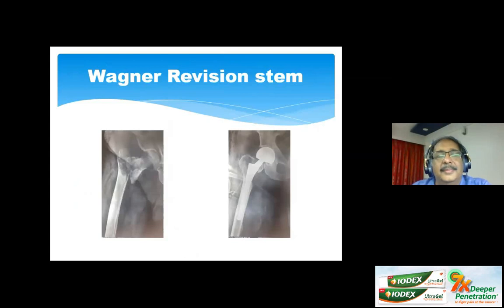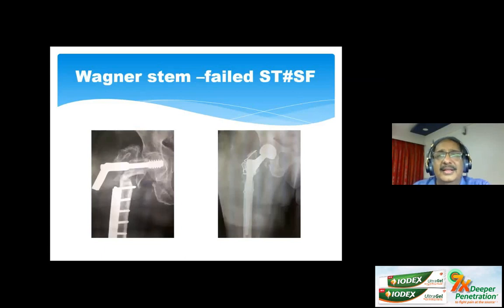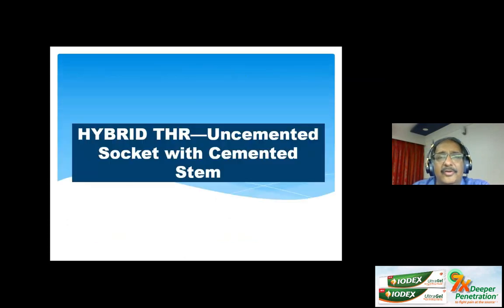These are a couple of examples where we've used a Wagner as a primary stem in complex trochanteric fractures in very old patients to start immediate mobilization. A failed subtrochanteric fracture here and a Wagner stem was used, but this Wagner stem luckily was a 195 millimeters, so we could get away without using an osteotomy and got a good implant. We've used it as a bipolar here because the acetabular side was not involved.